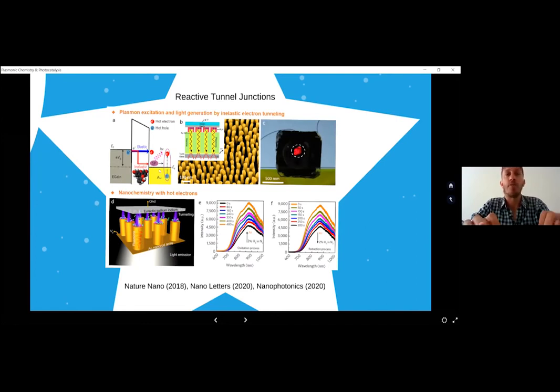So here they have shown that in between the gap and the gold rods, there is a tunnel, which is the phenomenon that I just explained. But if you fill that tunnel junction with different molecules, then you can have a reactive tunnel junction. The molecules can react due to the presence of these hot carriers that are being tunneled from one side to the other, and also due to the hot carriers generated by the plasmon decay.